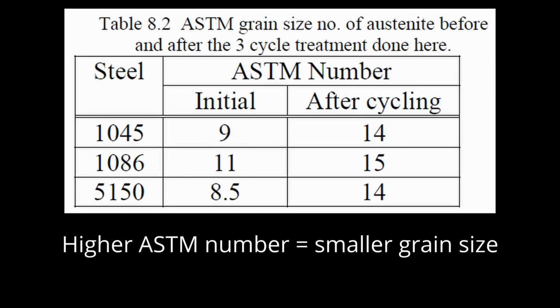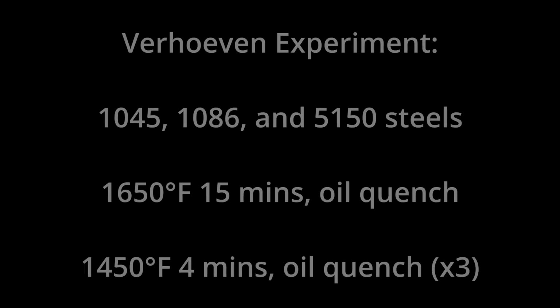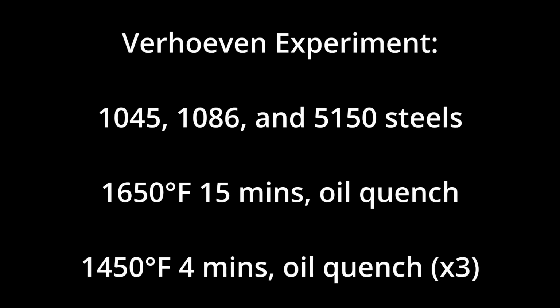And he found a significant decrease in grain size by doing the 1450 triple quench. And that 4-minute soak time is just 1 minute longer than what I did at 1475 for 3 minutes with the 1084. So why did he see an improvement and I did not in my experiment? Well, I think it makes sense given that he first started with 1650 for 15 minutes in quenching. 1650 is definitely hot enough to significantly increase the grain size in these types of material. And then when you repeat the heat treatment from 1450, then of course you can refine the grain size.